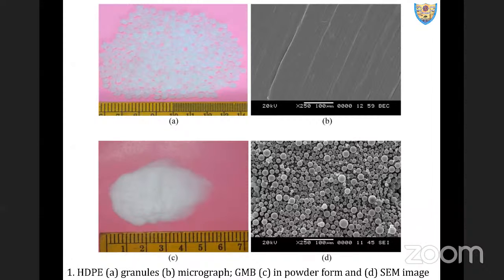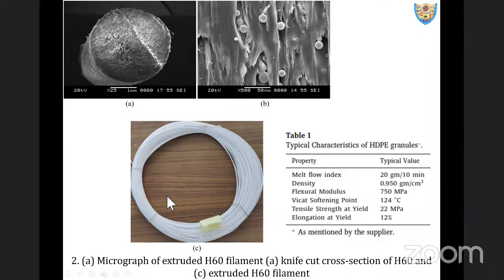So the blends of HDP and GMB are prepared using a Brabender. I have shown it to you in an earlier slide to develop the feedstock foam filament. This is that feedstock foam filament for 3D printing of sandwiches. Now blending is carried out at an optimized speed based on our earlier works. What we decided is to have a speed of 10 revolutions per minute at 160 degrees C. And we varied glass microballoons in the range of 20, 40, 60 by volume in HDP, and we designated them as H20, H40, H60.